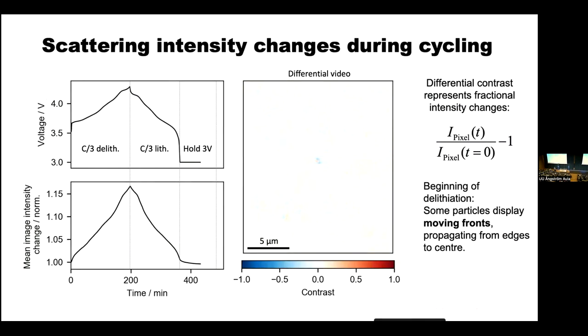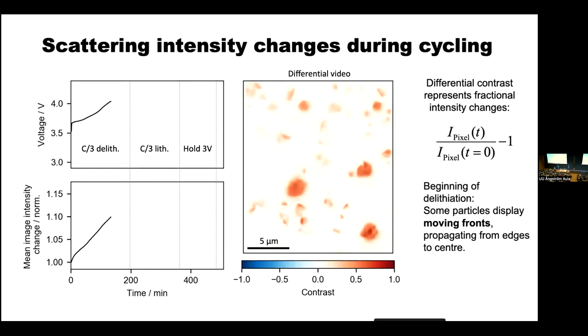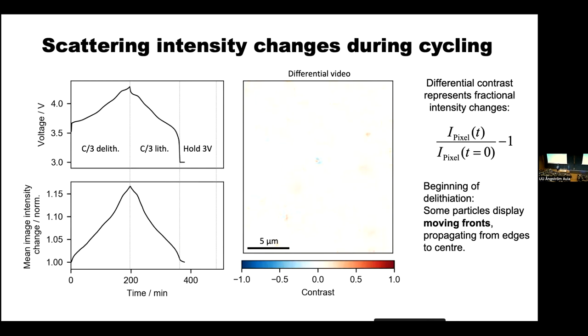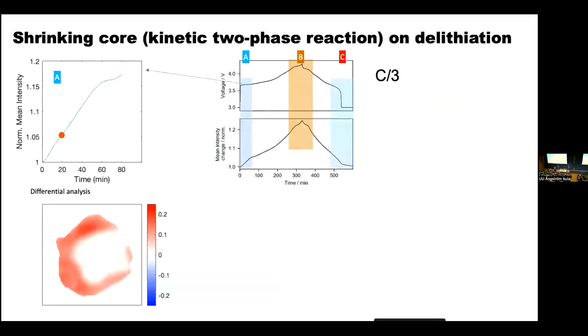If I just play that again, you can see that these particles develop these sort of cores, and then they gradually fill. For those who are interested, there's no evidence of an H2, H3 phase transition, which is what you'd expect. So there's no underlying polarizability or electronic structure change around that point. So let's tease the first part apart. This is the very first delithiation. And you can see at the single particle level, there really is a clear signature of this metastable two-phase front behavior that we were predicting based on our X-ray diffraction.